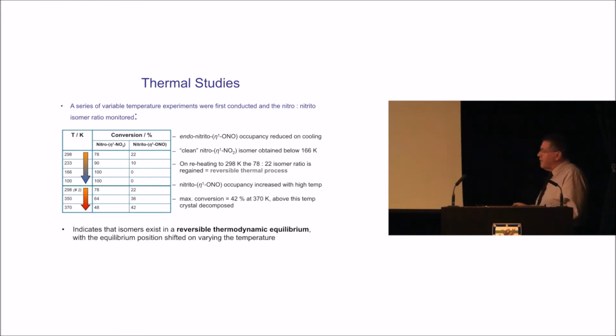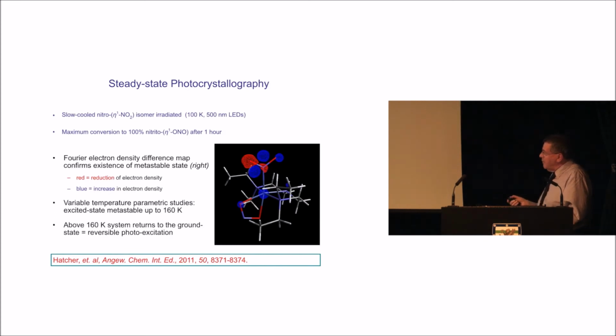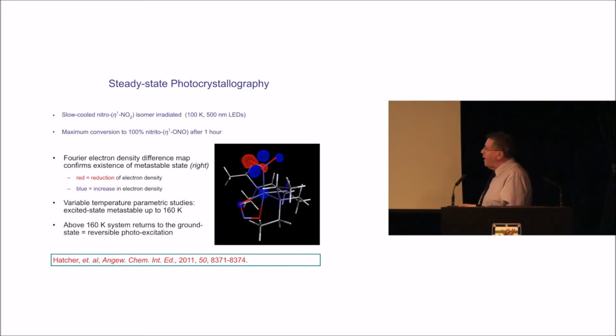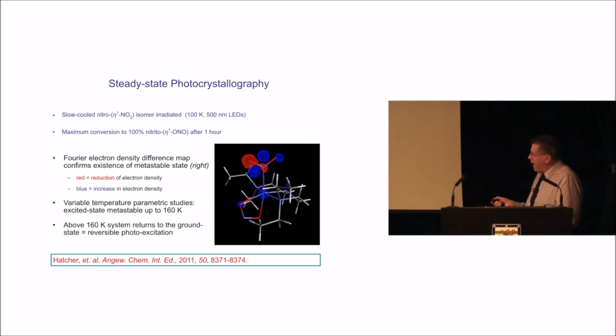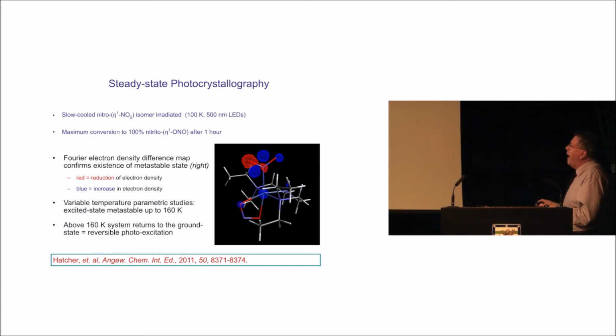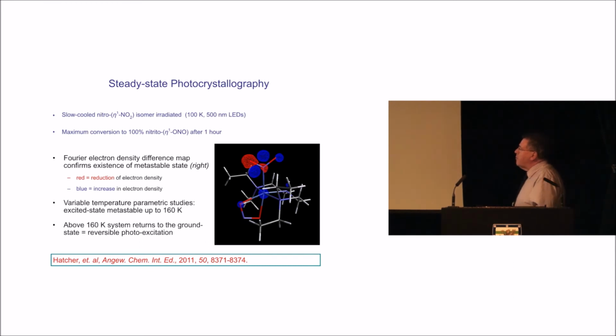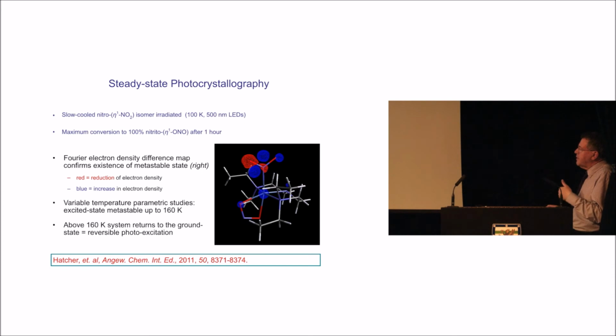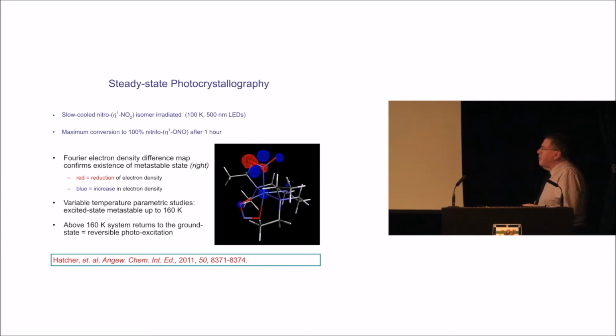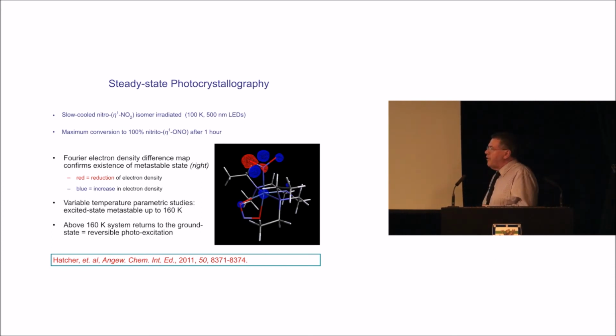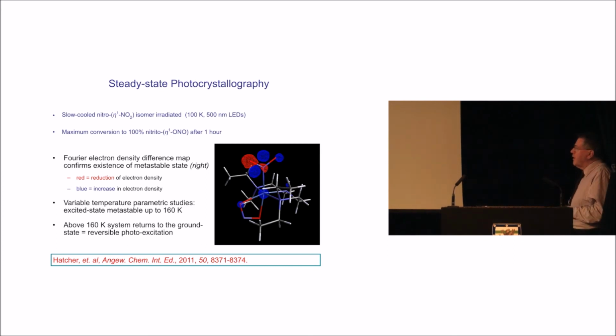We can do the photocrystallographic experiment, and starting at 100 K with 500 nanometer light, we get this 100% switch in about an hour, and you can see the electron density of the N-bound coming in and the O-bound coming in and the N-bound decreasing. And you can play with the temperature, do a series of parametric studies, and optimize the highest temperature at which this metastable state continues.